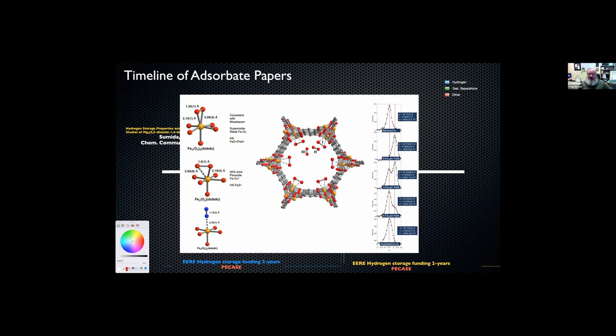this paper looking at different types of oxygen in an iron metal organic framework where the iron can be in 2 different states. If you put the oxygen in at low temperatures, you end up with physical adsorption typically. And that's consistent with Mossbauer, where you end up with a superoxide. As you heat it up, however, it turns into a peroxide, and you can see that the oxygen's really extended in this system. And 50% of the iron sites would be occupied by this peroxo species. And the binding of the nitrogen is completely different. And so there's some potential for these types of interactions where you've got a high enthalpic oxygen interaction.